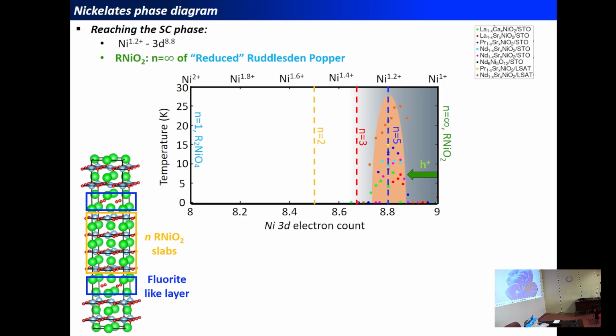superconductivity is also observed in a different material, which is called the reduced Ruddlesden-Popper material, which is made of n RNiO2 slabs like that, which are intercalated by spacing layers like that. And when you tune the number of slabs you have in the material, what you tune is the formal oxidation state of the material. So when you start from the first member, you have a nickel 2+, and then progressively, when you go through the different members, you decrease the formal oxidation state until you reach the superconducting region. And effectively, it has been observed that for this quintuple layer, it's a superconductor. So this is another way to understand the phase diagram of these nickelates.